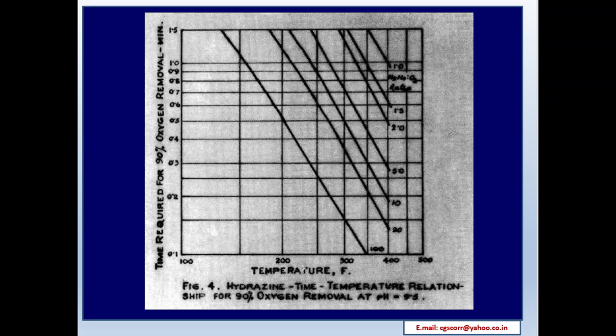Figure 4 illustrates the hydrazine-time-temperature relationship for 90% oxygen removal at pH 9.5. You can see here, as the temperature increases, the time required for 90% oxygen removal decreases.